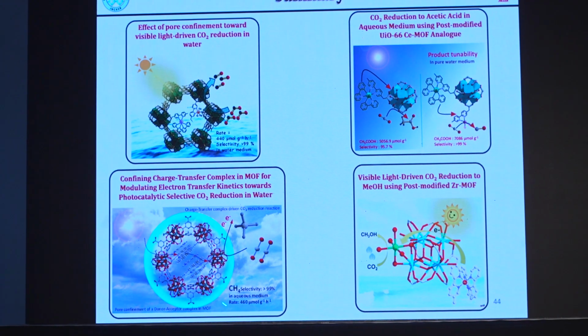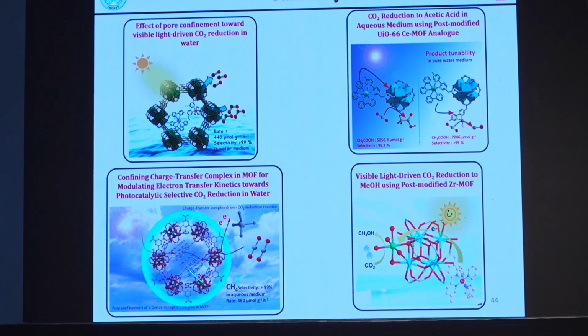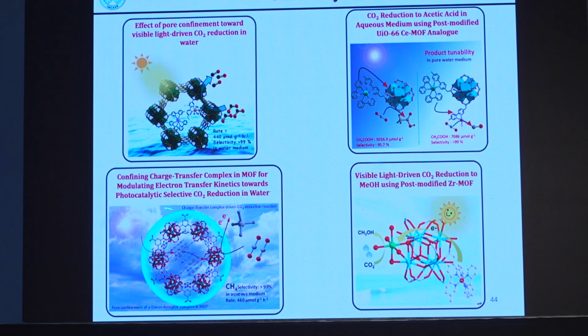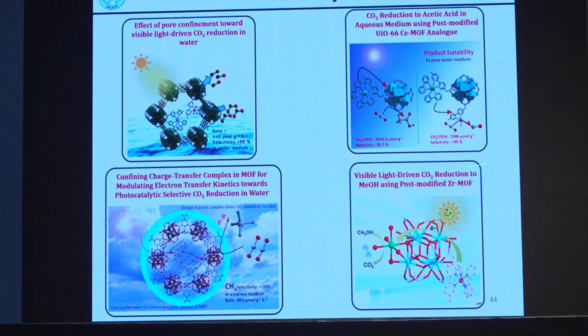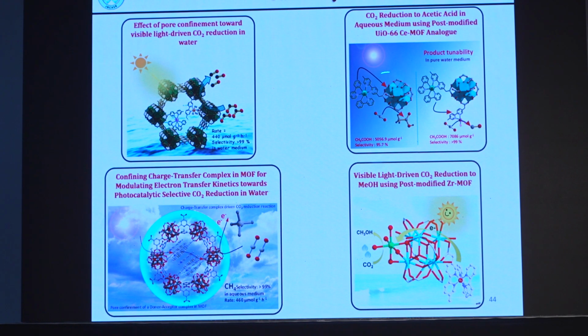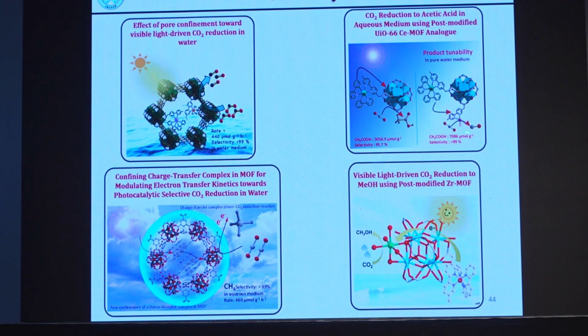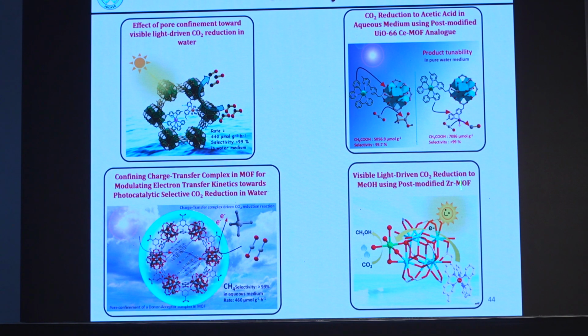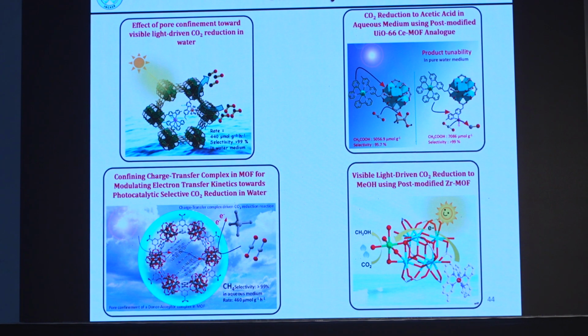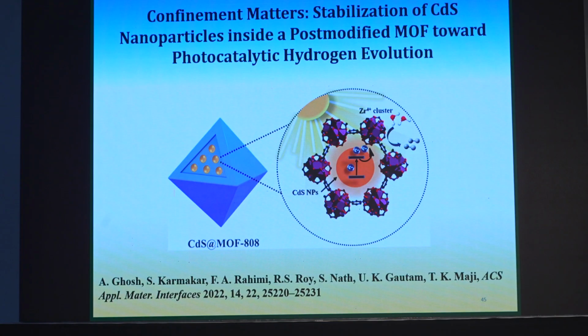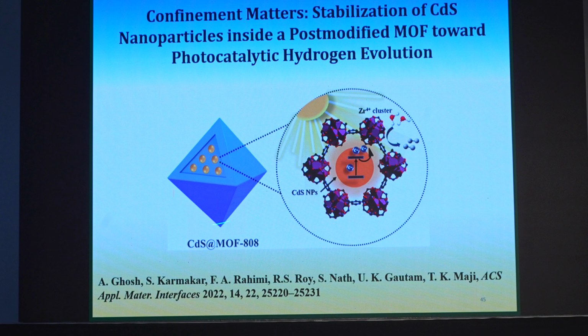Then we have just simple organic molecules you can put, donor acceptor. So show the donor acceptor electron transfer to here. And if you can do the electron transfer change from here, okay? Either you can go directly, or there's some additional single metal cobalt, you can go to either acetic acid or CO, or you can get the CH3OH if you do cluster modification with the iron, okay? So also we do a lot of work not only on CO2 reduction, you can get the HER also. So you can confine some semiconductor like cadmium sulfide, but with the same MOF, you can get this kind of product, okay?